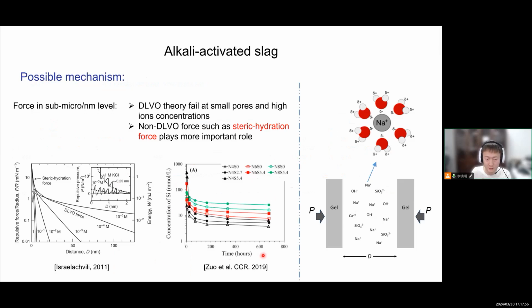According to the study by Yibing Zuo, we can see the ion concentration from the beginning till the first day decreased really a lot because the reaction consumes ions. And in very fine pore structures, these ions exist surrounded by water shells, which means that if there are a lot of ions, they will have a repulsive steric hydration force on each other, in balance with the compressive stress, for example the van der Waals force or the capillary pressure, which tend to make the gel shrink. This one is repulsive, so they are in balance with each other.